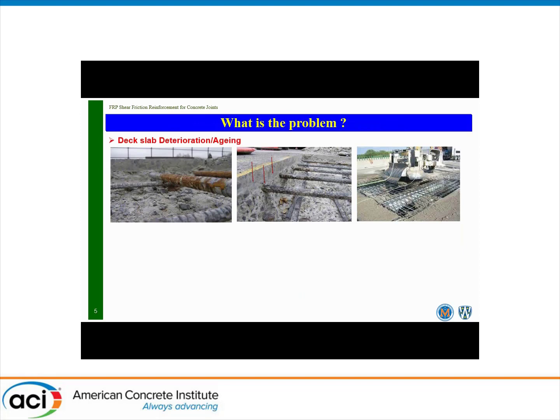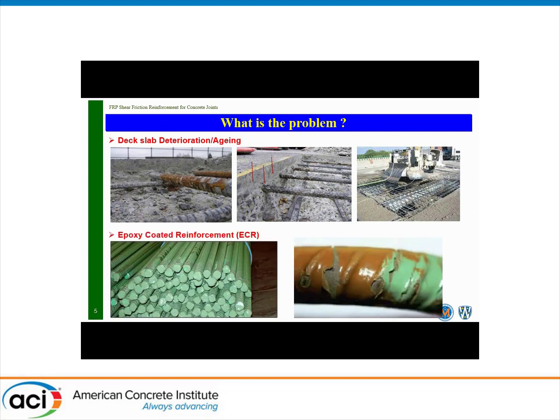The bridge deck slab, as a typical case in North America, is subjected to one of the harshest environmental conditions worldwide: freeze-thaw cycles, extreme cold temperature, de-icing salt. The bridge deck needs to be demolished from time to time and totally recast. Since that connection for shear friction is part of the slab as well, it is subjected to severe corrosion. The practice used to be using epoxy-coated reinforcement, which unfortunately has proven over time to fail to mitigate this problem.